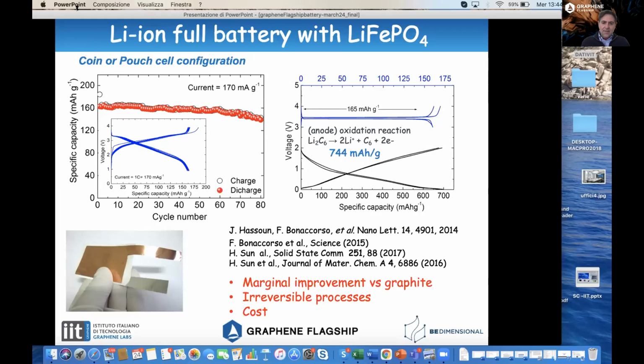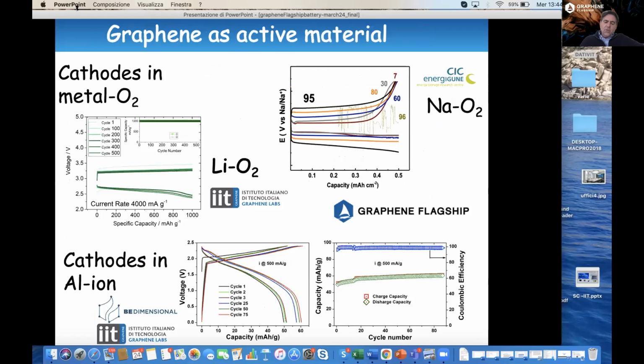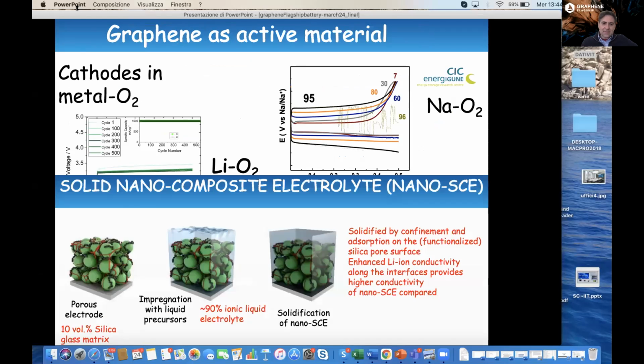There are many issues related to the presence of irreversible processes. So we understood that graphene is not a good active material for anodes in lithium-ion batteries, but can be used as active materials, for example, in cathodes in metal oxygen or sodium oxygen or in aluminum-ion batteries.